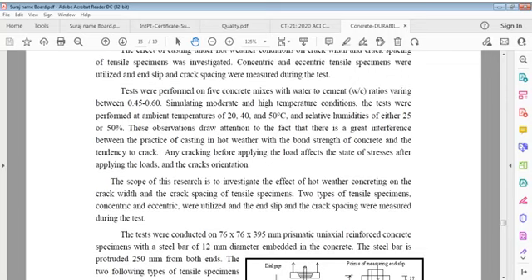Tests were performed at ambient temperatures of 20, 40 and 50 degrees Celsius, and relative humidities of either 25 or 50%. These observations draw attention to the fact that there is a great interference between the practice of casting in hot weather and the bond strength of concrete and tendency to crack. So, as I was saying, the water cement ratio was between 0.45 to 0.6, ambient temperatures 20, 40 and 50 degrees Celsius, and relative humidity 25 or 50%.